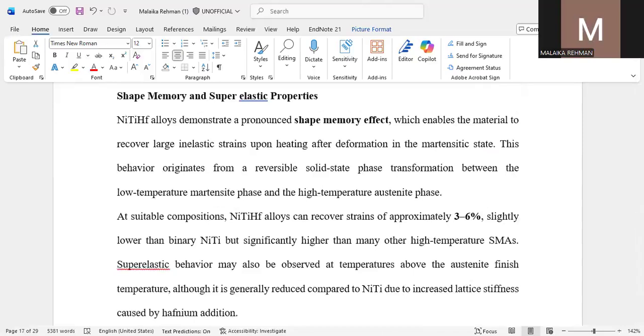It exhibits the shape memory effect, which enables the material to recover large inelastic strain upon heating after deformation in the martensitic state. This behavior originates from a reversible solid phase transformation between the low temperature martensite and the high temperature austenite phase. At a suitable composition, the alloy recovers strain of about 3 to 6%, which is slightly lower than binary nitinol, but significantly higher than many other high temperature shape memory alloys.